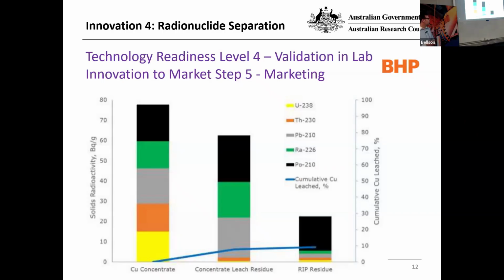And so then we came up with a third step, which is a resin-in-pulp technique, which allows you to essentially suck off the lead and the radium, which are on the surface, and put them onto the resin beads, and then you can just do a physical separation and dramatically decrease the radioactivity of the concentrate. So the only remaining radionuclide of significance is polonium, which actually does decay if you leave it out, and can also be driven off with heat if you need to. BHP has the right to use that technology, but it's a UQ technology. So if you know someone else who wants to take up that kind of thing, let me know.